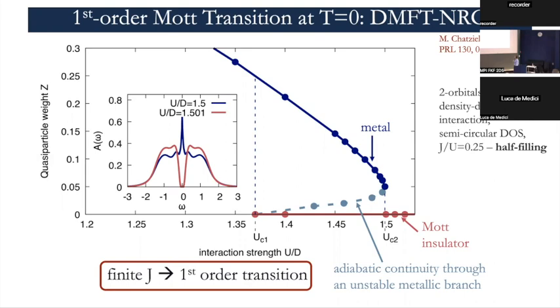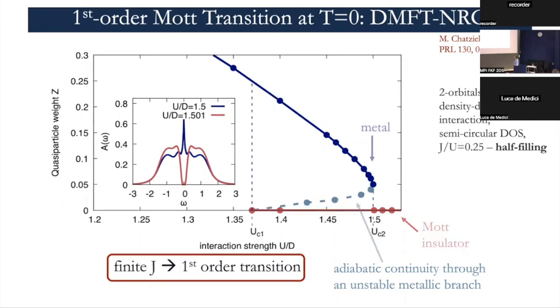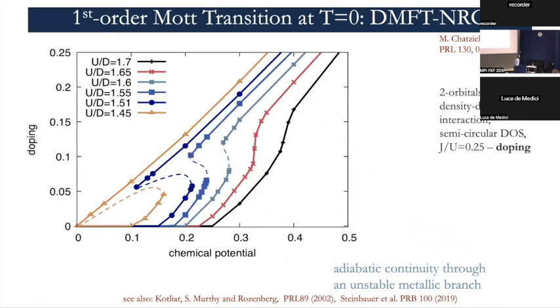Now, this is interesting also when we look at the results doping the system. So this was at half filling. Now let's go out of half filling. If you dope the system in the zone where you have the stable metallic, the stable insulating, and the unstable metallic solutions, the metallic solutions will be immediately doped once you move the chemical potential, whereas this plateau is the Mott plateau that you get when you try to move the chemical potential in the Mott insulating solution. You have a gap, and only at a finite chemical potential do you get doping.